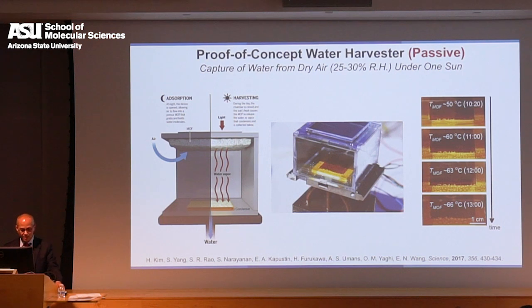So we designed, in collaboration with Evelyn Wang at MIT, a handheld device that employs 2 grams of MOF. The device works by, you open the device during the night for air to get into the MOF, water gets into the MOF. You close it during the day, expose it to sunlight, it heats up, and water comes out of the MOF and condenses on the walls. And you can see here the droplets of water as the interior heats up to 50, 60 degrees and so on. The droplets are getting larger and larger. Okay? So not much water is coming out, but we are only using 2 grams. But it works. It works outside the lab.